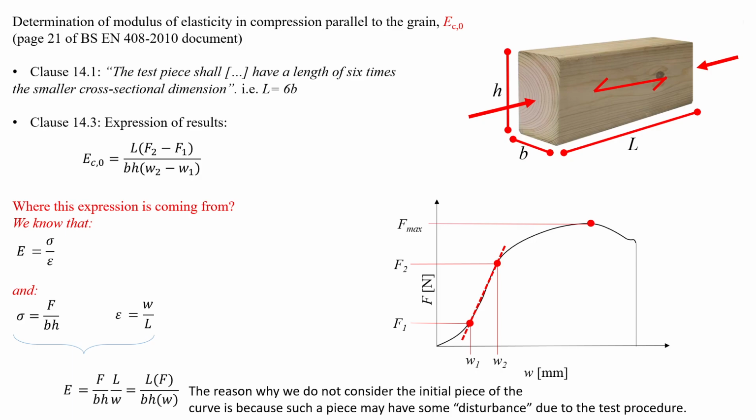We will have to test it, because if it's not good enough, we're going to have to change where these 2 points are. We'll have to move them either further away from that curve, or bring them in, potentially. The data will have to be within 1%. So what we'll do is graph live data versus a fit for the equation. The R squared, you know what R squared is in Microsoft Excel?